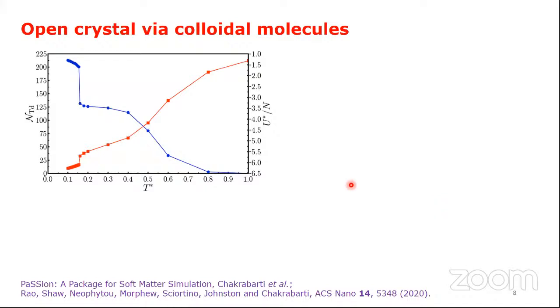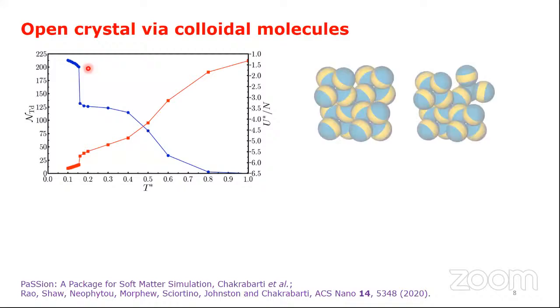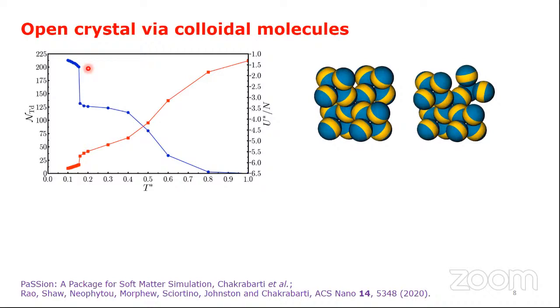A series of Monte Carlo simulations with 500 particles under periodic boundary conditions show that a tetrastack crystal can indeed be self-assembled from our designer tri-block patchy particles. If we monitor the number of tetrahedra formed in the system as the system is gradually cooled, we find that the tetrahedra are initially exclusively formed by the interactions between the stronger patches. A rapid growth of the number of tetrahedra signals crystallization driven by the interactions between the weaker patches. Note that the crystal structures are stable even in the absence of a hierarchy of interaction strengths.